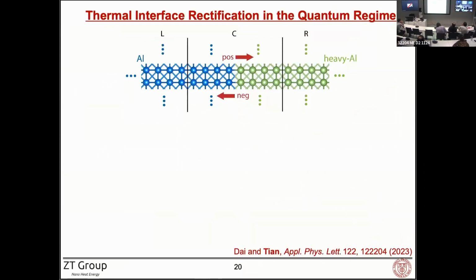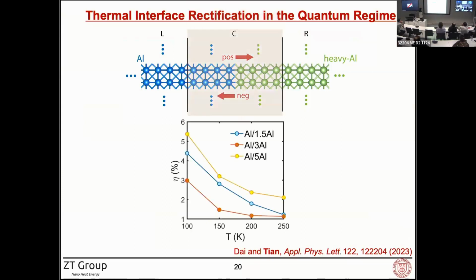And with this new development, we are also able to discover this new intrinsic thermal interface rectification in the quantum region. Essentially, in the quantum region, the phonon populations follow the Bose-Einstein distribution. So as you flip the direction of your heat flow, the phonon populations change on both sides. Now, with the interplay of the inelastic scattering, we're able to see the nonlinearity at the interface that creates the thermal rectification. The details can be found in our new publication here.